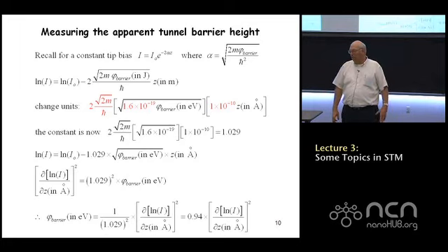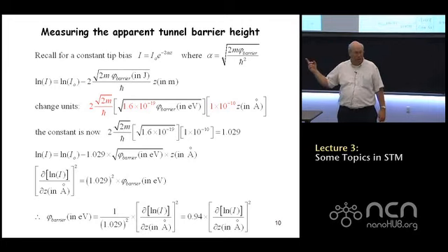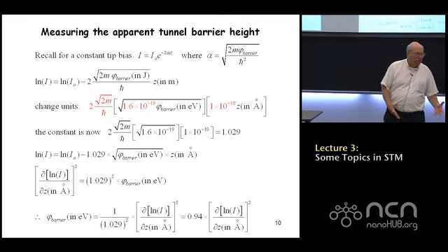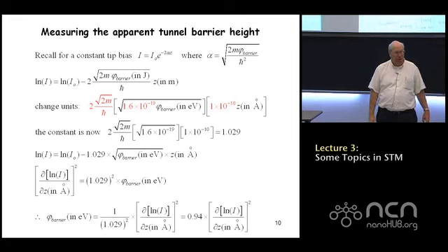So what you should know is that most barriers for metals, for refractory metals, are on the order of 4.5 to 5.5 electron volts. So you would expect that barrier heights coming out of this measurement would be somewhere on the order of 4 to 5 eV. In practice, the numbers that we were all getting at the time were closer to 1 eV, right? It was about a factor of 4 or 5 lower than what we expected.